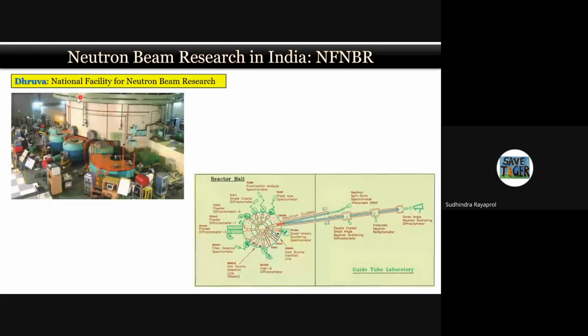At Dhruva, this is the reactor hall, and there are plenty of neutron scattering experiments available. You have a single crystal diffractometer, you have a triple axis spectrometer for carrying out inelastic scattering, and you have a polarized analysis spectrometer. You can do polarized measurements, meaning you can polarize a neutron beam and carry out diffraction and scattering experiments. You have 3 powder diffractometers. There is a new inelastic spectrometer coming up here in place of the filter detector.